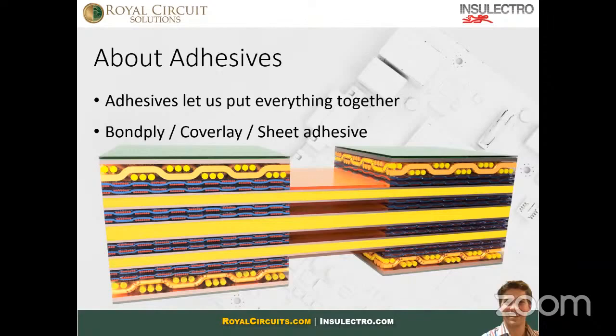We can use sheet adhesive, like Teresa mentioned, to build up the amount of resin we would need. So instead of buying a high resin count or a high resin pre-preg, we just put another piece of sheet adhesive into our bond plies and coverlays. And that gives us the ability to dynamically add or subtract adhesive during the manufacturing process without having to custom order really intricate or really one-off designs. We have the ability to stack everything together in our flexible areas to get to the thicknesses we need.